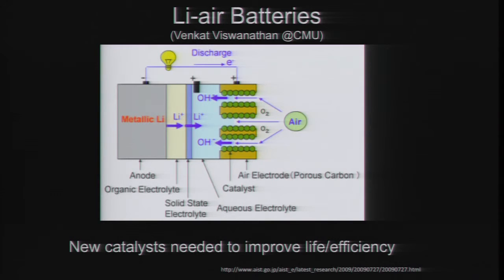But you have to move this lithium through a couple different electrolyte layers, and then it has to have a reaction with some things that happen with air. And so oxygen comes in, and you have to convert air oxygen into some solution-based ion that will go in and interact with the lithium somehow. And that reaction has to take place on some surface. And typically people have been using carbon surfaces to enable this, but long-term studies on the stability of those carbon surfaces show that they're not fully stable.